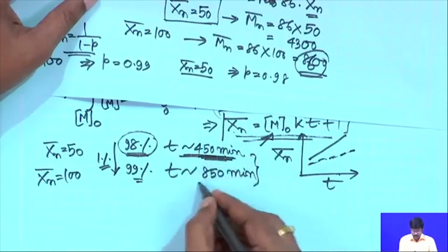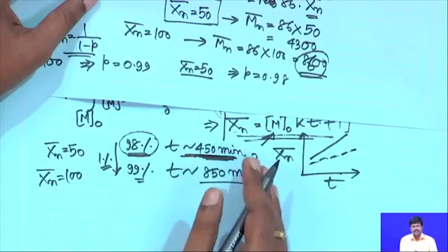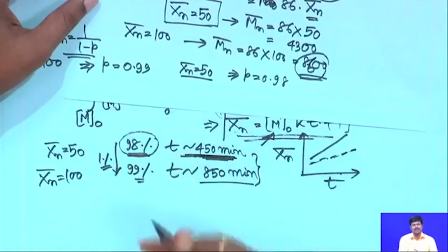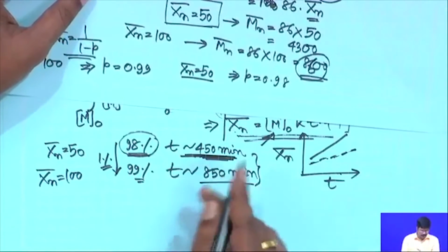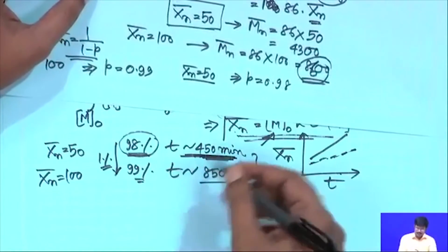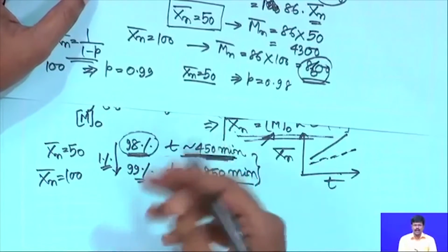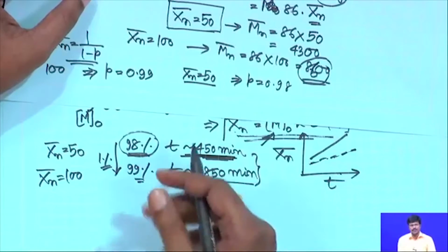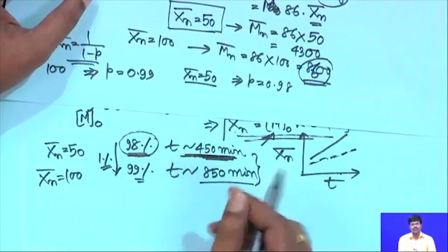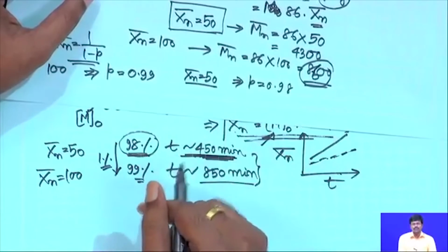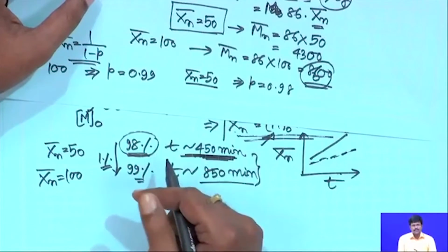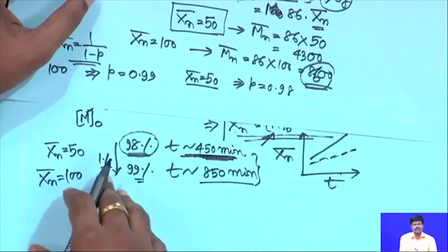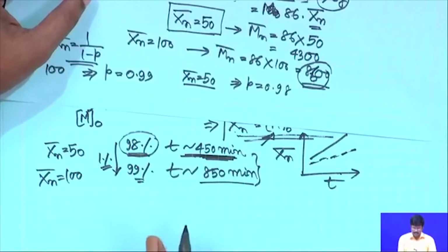Now, this kind of problem is there for step polymerization. Towards the end, each percent of conversion will take almost double the time, say from 98% to 99%. So, I hope that this particular small calculation has given you the idea of the importance of this kind of analysis of kinetics, because if you did not do this kind of analysis, you would not know what are the things that you need to do to achieve high molecular weight. So, these equations show you need to go at least to 99% of conversion in order to get reasonable molecular weight for your polymer.